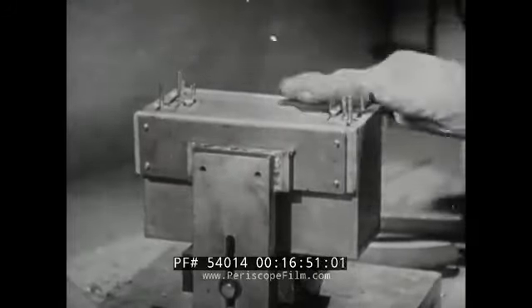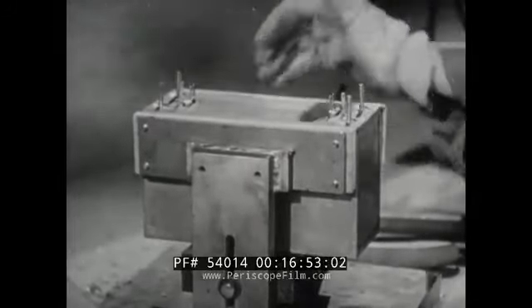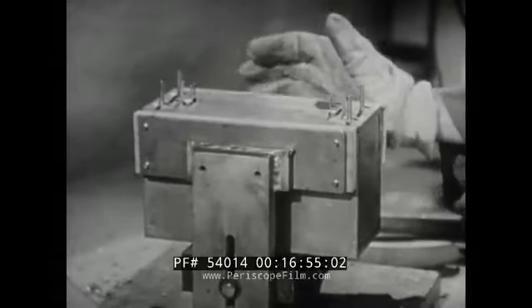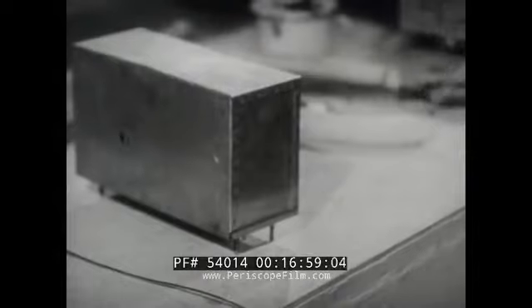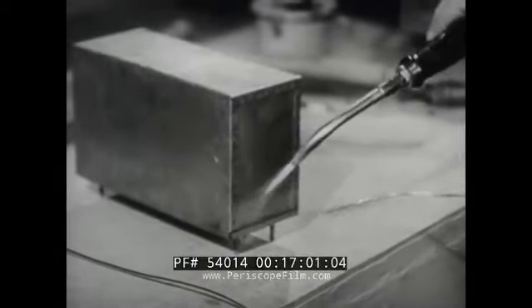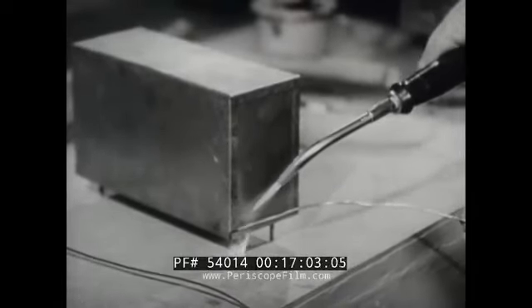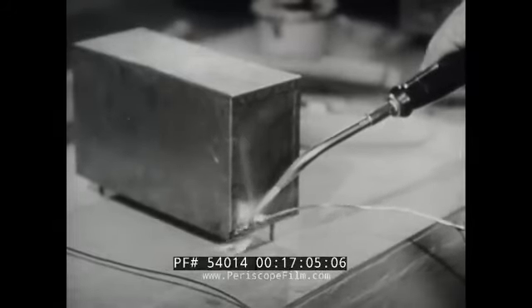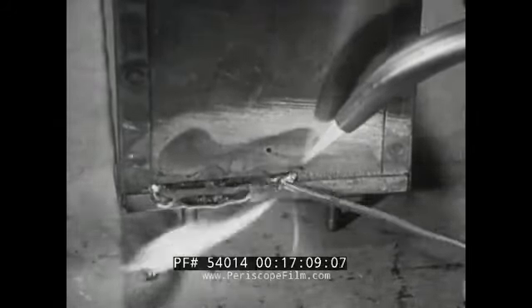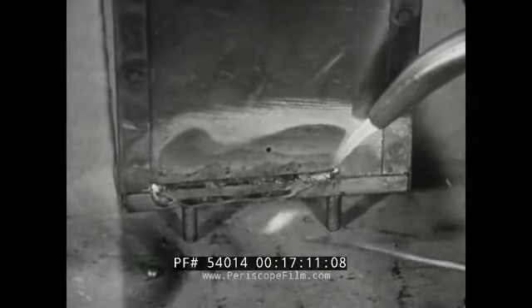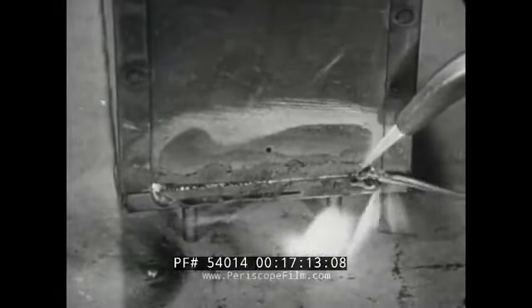Do not unclamp the holding fixture until the seams have cooled sufficiently to set the solder firmly. The 2 end seams are sealed with a flame. The can and contents have been placed upside down on the bench in such a position that the solder flows down into the seam. In this way, a pool is formed inside which provides an effective, airtight, waterproof seal.